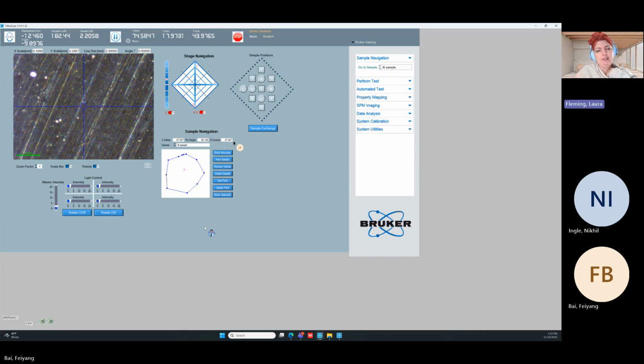If you do not have this Z contact height, if it is 0, the system is unsure where that sample height really is. So it starts the slow approach all the way up here. And then it goes click, click, click, one at a time, very slowly until it finds that sample surface, because it doesn't want to leave any plastic deformation. That's what was happening to us. And it takes a very long time.